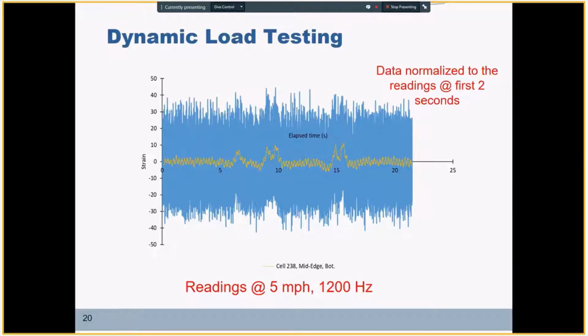Loading is done at two speed levels, 5 and 35 miles per hour, and data are gathered with a frequency of 1200 hertz. Here I have one of the sensor readings at mid-edge bottom part of the pavement for cell 238, with readings at 5 miles per hour. The blue lines are the raw sensor readings. I took the first 2 seconds of data as the base of the measurements, and normalized the readings based on that first 2 second data.